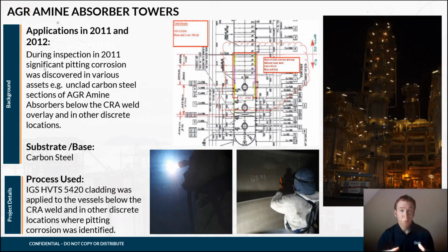So the first example is an AGR, amine absorber column or tower. The client started to see aggressive pitting in the middle section of the tower. So they were getting breakout of the corrosive materials into this section of the tower, losing wall thickness and potentially getting to a point where they were going to have to do replacement, sectional replacement, or ultimately vessel replacement. They wanted to install a corrosion resistant alloy, and they wanted to look at the different techniques to do that. Field weld overlay was considered, but that was going to take too long and would also require the post-weld heat treatment, which they wanted to avoid.